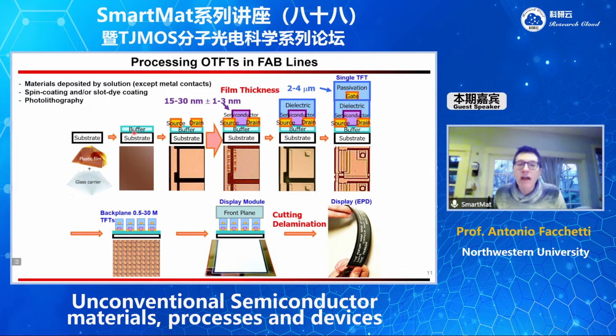So that you have a flavor of how the TFT is built in a real line, you start from your substrate and then a buffer is placed. And then you put your electrical contact, you put the semiconductor, the dielectric, the gate, the passivation, and then you end up delaminating the TFT array and integrating the front plane. But what is very key here is that all the processes involve, as I said, spin coating or slot die coating, and they involve photolithography. There is no printing in production of TFTs at the moment. So it is essential to use photolithography to pattern the semiconductor.